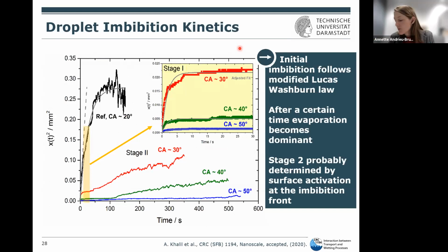Yeah. So the first question is why this Lucas-Washburn applies and why it's steady state. Actually, I cannot answer you why. I can just tell you that you're right. There's the contact angle involved. There's a pore size involved. From the literature I know, this Lucas-Washburn behavior is observed in case you exclude evaporation. So in case you have no evaporation, because of course this is not considered in Lucas-Washburn, you see this Lucas-Washburn-like behavior. But you have to be careful with one thing. This is of course a fit to that data. It's not a prediction.